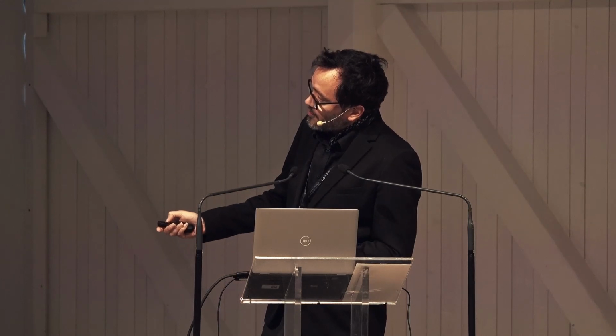Okay. In order to fit the force fields, we use a collection of techniques. We use non-equilibrium molecular dynamics in LAMMPS software. We use particle swarm optimization and also a bunch of machine learning techniques in order to accelerate the fitting of the force field parameters to match properly the microscopic properties of the slurry.